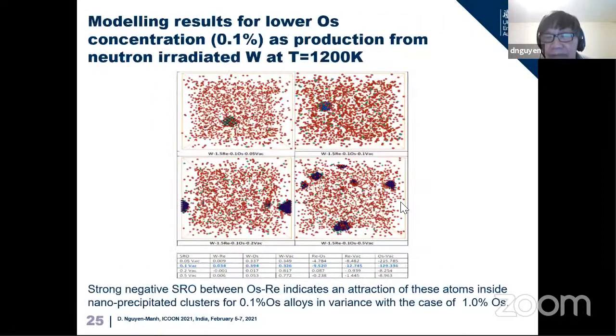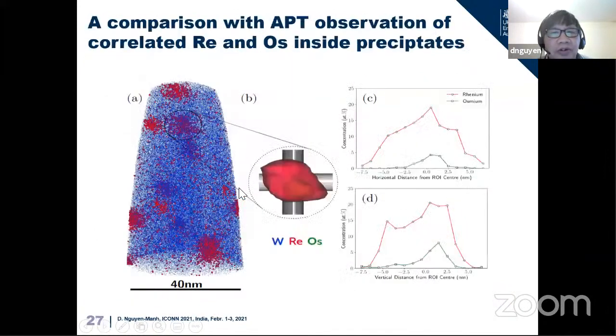And that is exactly what we produce at the very low concentration of osmium, which is exactly the transmutation concentration that we see in the fusion reactor, where only a very small amount of osmium is produced, but we see the correlation of osmium inside a precipitate due to the negative short-range order. Comparing with atom probe tomography, we see the same picture, that there is also correlation between them.